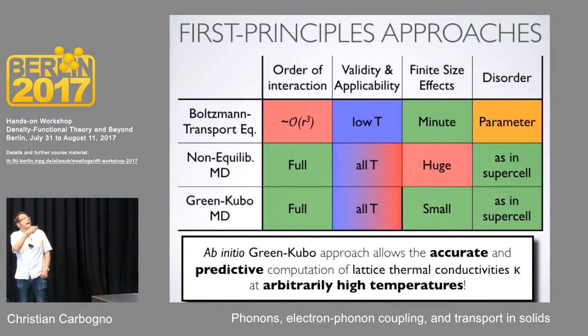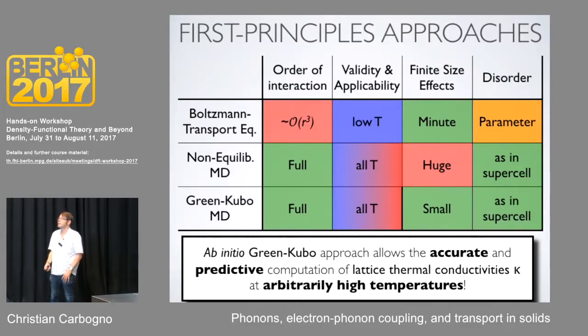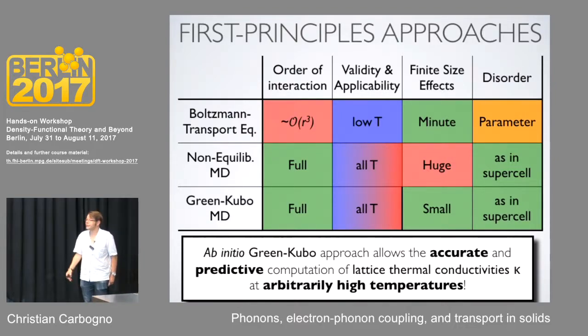Looking at thermal conductivity as a function of doping, it goes down significantly as yttria is introduced — the barriers go down, so switches become more probable, the system becomes more anharmonic, giving lower thermal conductivity. Until at some point the doping becomes strong enough that the situation with different minima is annihilated — you get a true new minimum at the cubic state, roughly at 17% fully stabilized cubic. At that point the thermal conductivity starts going up again. In a nutshell, you can tailor anharmonicity by doping. Different approaches — Boltzmann transport equation, non-equilibrium MD, equilibrium MD — have different pros and cons suited for different temperature ranges and system sizes. Thank you very much.